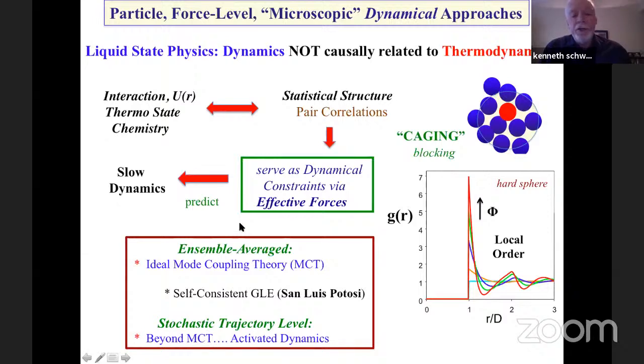Then you have two choices to try to understand the problem at the level of the ensemble average, which is how experimentalists do it, unless they're observing trajectories in a confocal microscope. The prototypical example for that is ideal mode coupling theory. There's also very nice work done in this direction at San Luis Potosí. And then there's a second approach, which is my own work, to not work at the ensemble average level, but to work at the stochastic trajectory level, which I will argue is, of course, approximate, but is a beyond-mode-coupling-theory approach because it focuses entirely, essentially, on activated dynamics.